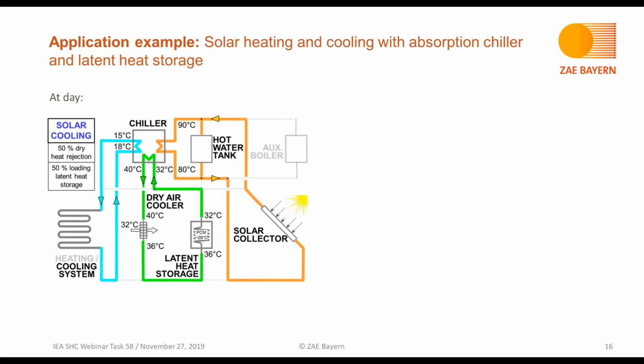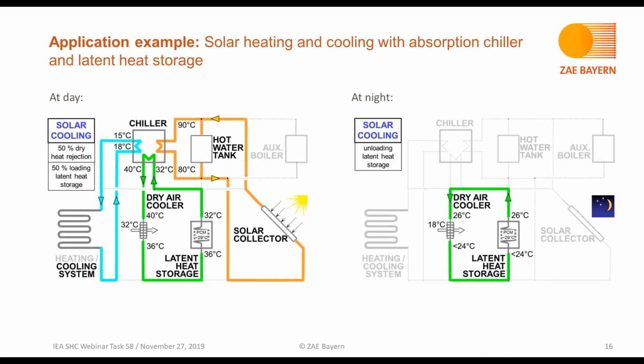Of course, to regenerate the storage at night, the system is operated in that way that the latent heat storage is unloaded using colder air of the night. For this system, we were using calcium chloride hexahydrate with a melting temperature of 29 degrees C, which suits well to the application temperatures.